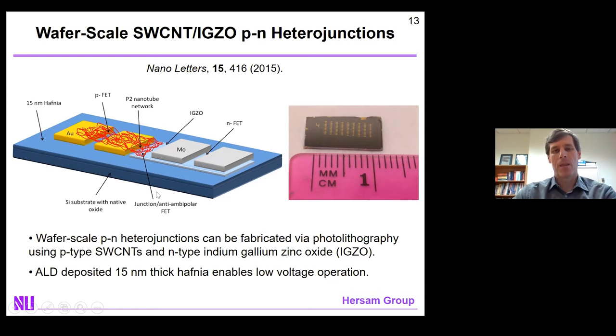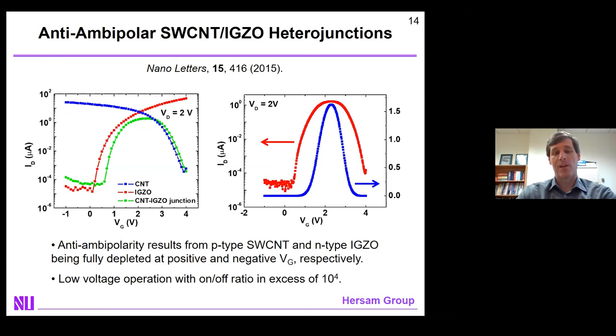And if we look at the resulting current voltage characteristics, we see that anti-ambipolarity is not unique to nanotubes and MoS2. It can be done with any two semiconductors as long as one of them is atomically thin, in this case, the carbon nanotubes. And you can see that we get now very nice anti-ambipolar characteristics. You'll note the operating voltages are now down to much more reasonable levels. We get a nice peak in the current, and on the linear scale, you see an almost perfect Gaussian transfer curve. And as a result, many people refer to these devices as Gaussian heterojunction transistors. In fact, you'll hear me refer to them as such later in the talk.